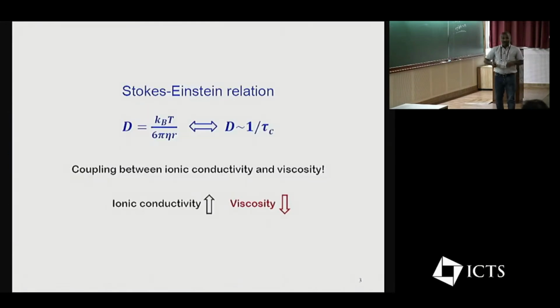So I would like to recall what happens to Brownian particles when immersed in a fluid, and what the relationship is between the diffusion coefficient and the viscosity. They are inversely proportional to each other. That's what I wanted to highlight. Sometimes people interpret these viscosity effects through the underlying relaxation phenomena. Here I'm denoting that as tau c. So you can imagine the diffusion coefficient in fluids to scale as 1 over tau c.